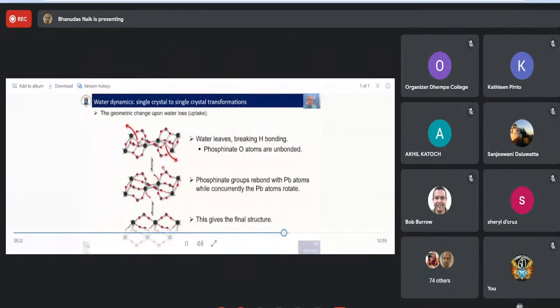So we can see the geometric change as the water uptake. In this case, looking at the water leaving. So if you remove the two water molecules, you'll be left with this skeleton here. You can see that this oxygen here has no one to bind to. And this one here is only bound to this one, and this one has no one to bind to as well. So then you expect that this ligand will push towards this lead center, and this one to this lead center, and this will rotate the center pair of lead atoms here. As you can see, this center rotates on the side here.